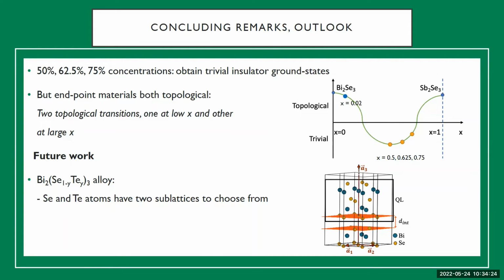Okay, this is not a very novel result on our part. This had been found before, but we did find that at concentrations in between, it is trivial, which indicates that, if you have a phase diagram in which the endpoints are both topological and the middle is trivial, that indicates that you have at least two transitions, from topological to trivial and then trivial back to topological, at some intermediate concentrations. So we're exploring this phase diagram right now and trying to pinpoint where exactly the transitions take place.